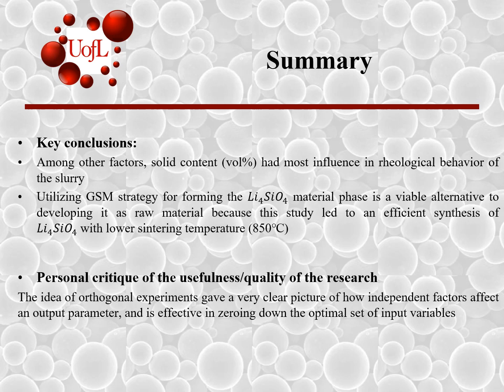For this application, the sintering temperature is chosen to be 850 degrees because it would result in having smaller grains. Larger grains are not favorable for this application because the tritium ions would take a lot of time to go around these larger grains. And so in summary, among all the other factors, solid content had the most influence on the rheological behavior of the slurry, and using this generative shaping material forming strategy for forming the target material phase is a good alternative to developing raw material, because this study led to parts with better mechanical properties and efficient synthesis of the target material phase.